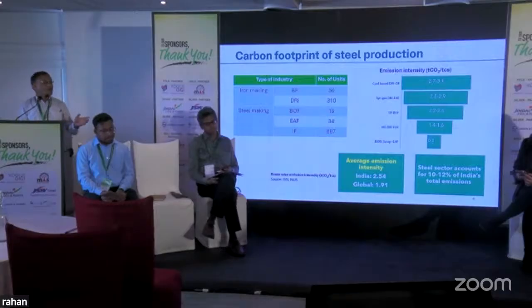When you talk of DRI-based steel making, the entire West is on DRI-based arc furnace. Only India has indigenously developed, one can say, the technology, or perfected the art of making the DRI-based induction furnace coal-based route. And the graph also shows the energy emission intensity of the different routes, and the coal-based DRI induction furnace route is one of the highest emission intensive, almost 3 tons per ton of steel. As you can see, very high.